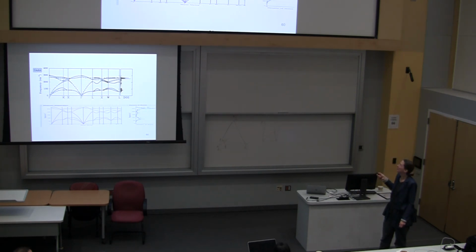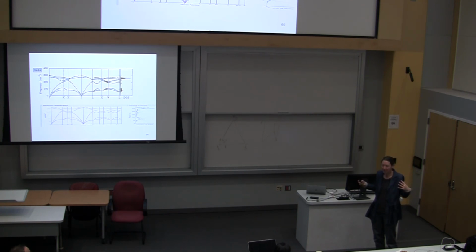This problem with the phonons is something I'm working on with a postdoc at Rutgers. We're looking at phonons in 2D monolayers, and a lot of what's published is really just wrong, because the interpolation methods they're using to go from a sampling of points to the full dispersion relations are bad. I can show you specific papers where they have these crazy wiggles that they just published, and I look at that and I know that's not real.